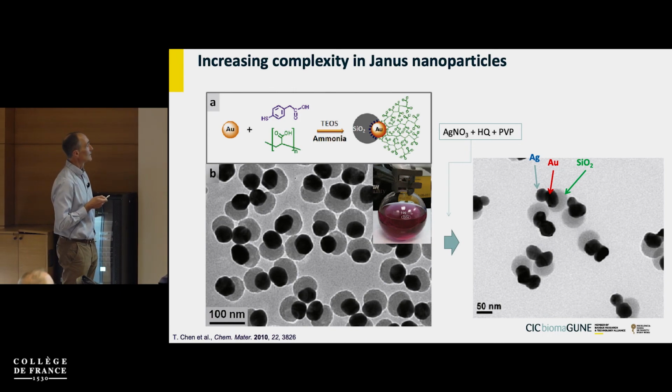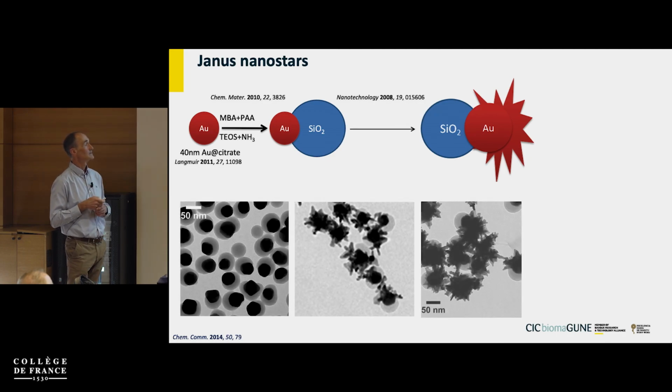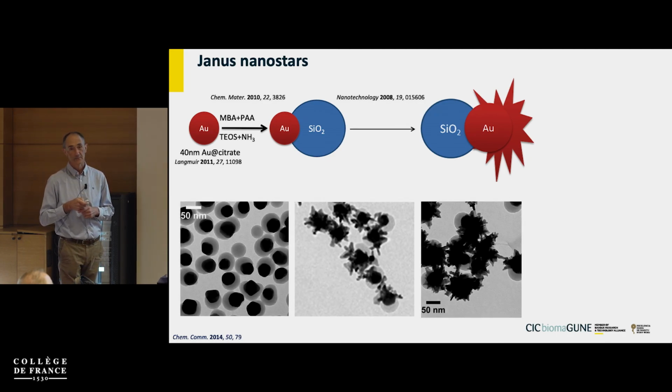So we thought, well, why not do this, to grow spikes on one side? And is this useful for anything? We don't know yet, but it may be, depending on how you play the chemistry afterwards. But of course it worked, so we combined the method published already in 2010 with our nanotechnology paper, meaning reduction by using HQ as the reducing agent, to grow tips selectively on the exposed side of the gold particle.